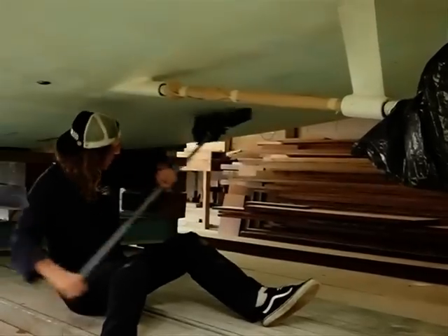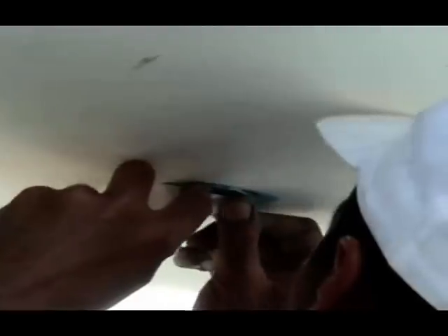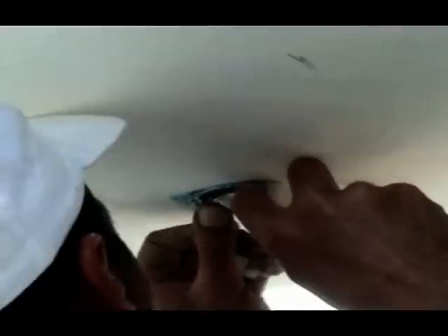Finally, the hull must be abraded to provide a good key for the new epoxy coating. The most efficient method is to use a random orbital sander with 60 to 120 grade discs. However, sanding by hand is again an option. Be sure to remove all the resulting dust before proceeding with the application. Finally, carefully mask around any hull depth sounders, as it's best to leave these small areas untreated.